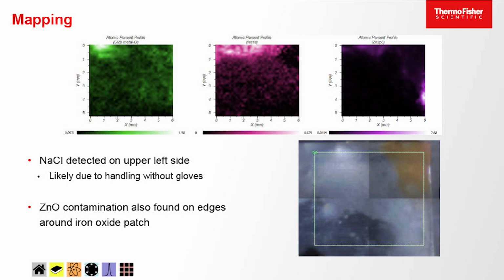I suspect because it's associated with the sodium, this is where someone had touched the sample before handing it on to us. So again, I'm going to keep saying gloves through it, but sodium chloride present, if it's not expected there, is usually the indication someone's touched the sample. The zinc, interestingly, is strongest on the edges as well. So that's possibly where a fixing has been for the piece, and there's some sort of abrasion there, some scratching, and it's transferred some material from the fixing.